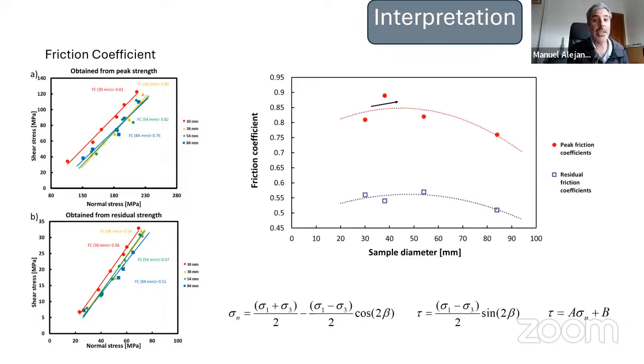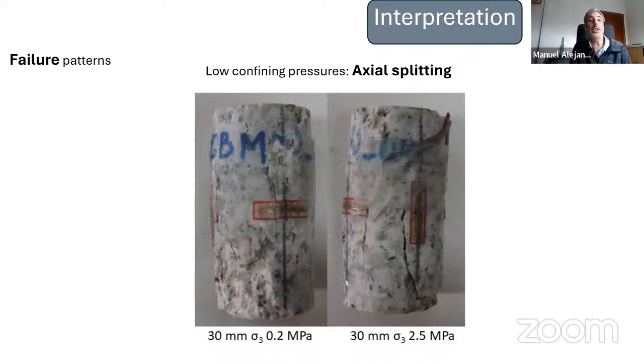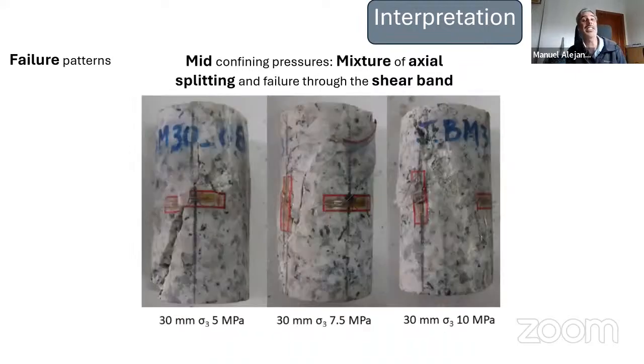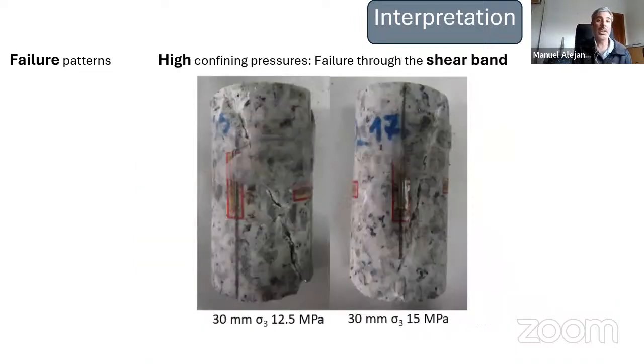And if we plot the friction coefficient against the sample diameter, we can observe, for peak and residual, this ascending behavior observed in the strength. Regarding the failure patterns, we can find for low confining pressures axial splitting, moving through a mixture of axial splitting and starting shear banding for mid confining pressures, through a full shear band pattern.